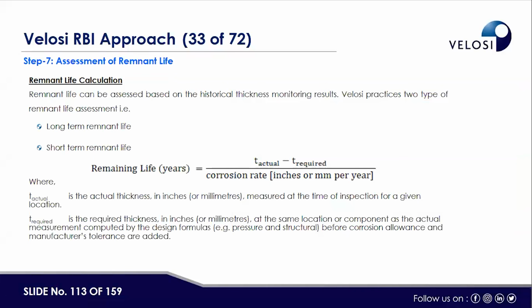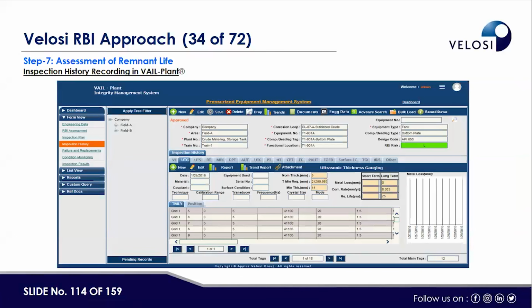Another live calculation is the same, where we have T actual minus T required. Another formula is also there. If we have another calculation available, not a corrosion allowance but T actual minus T required, then the corrosion rate is applicable. This gives us FCA, future corrosion allowance, and we can see remnant life. This is the inspection history, which basically gives us the corrosion rate formulas, and the metal loss is here, right? And remnant life is also given by the software. And this is the T minimum required, maximum.